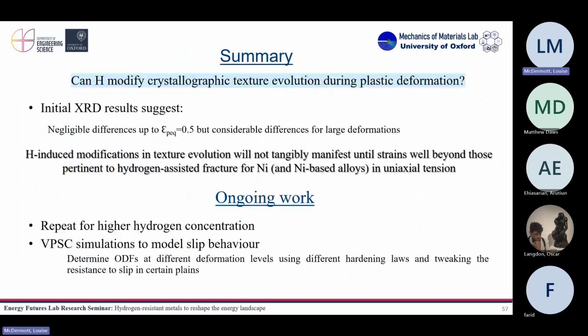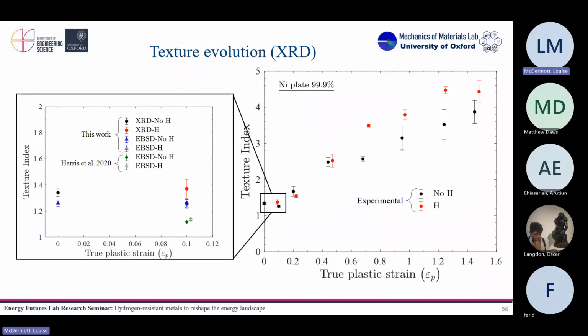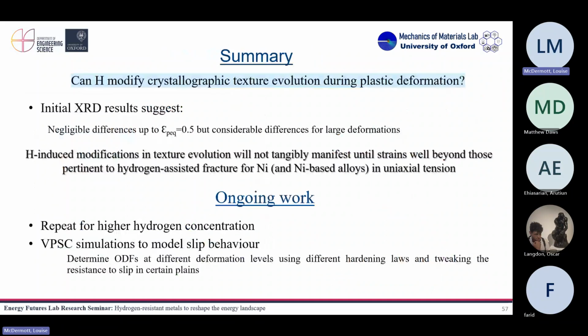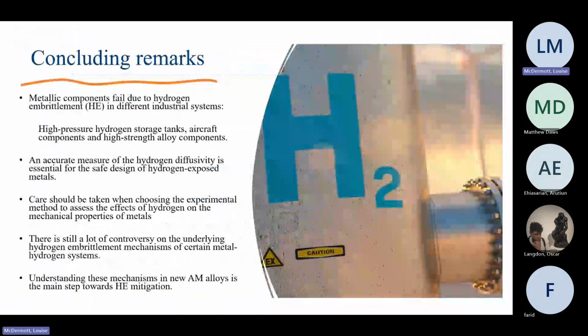So my next steps, and actually after this I'm running to the material science lab to do some of the measurements, are to repeat this for a different hydrogen concentration. I want to have another curve for hydrogen, but with a much higher hydrogen concentration, to confirm these results. And I want to do some simulations to see the slip behavior and change parameters, to get some information on the slip systems that are active or could be active when we have hydrogen or we have not. And in general, that's all.